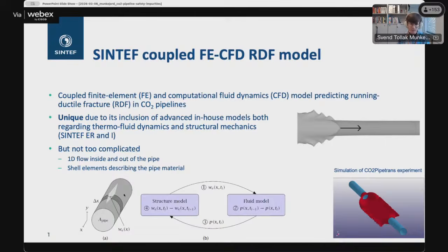And the way it's set up is that it starts with a given crack width, like here. This crack width is passed to the fluid model, which calculates the leakage rate, and the pressure is passed to the structure model as a load, which then decides whether the crack grows, etc. So here we made some what we think are reasonable simplifications in order to be able to calculate industrial scale pipes, but there are things we want to refine, and I'll touch on some of them in the following.